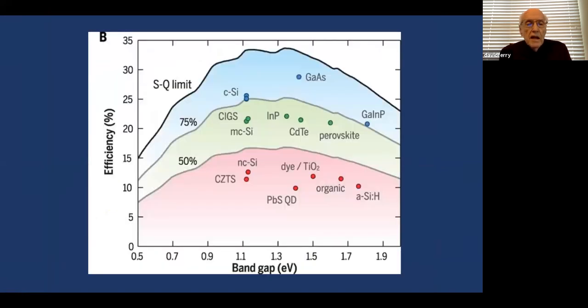Now, this is the so-called Shockley-Queisser limit. That's this black line that comes up over the top. We'll explain the bumps and wiggles a little bit later. But these are mostly single crystal, single junction cells. Crystalline silicon, amorphous silicon, gallium arsenide. And the Shockley-Queisser limit was worked out many years ago by Bill Shockley and Hans Queisser, basically on a thermodynamic argument, which shouldn't be really all that important for solar cells, but it seems to have survived.